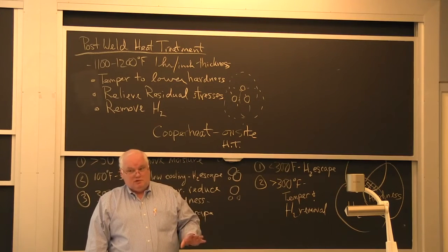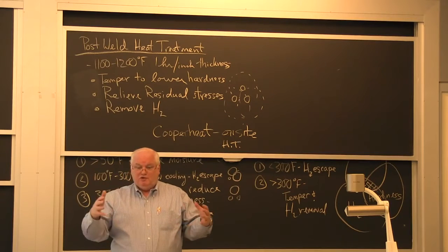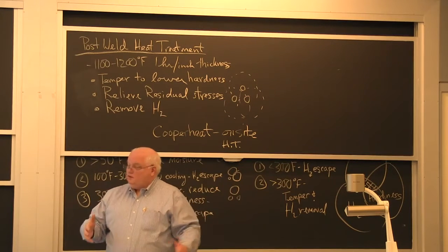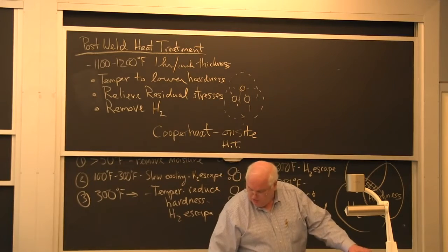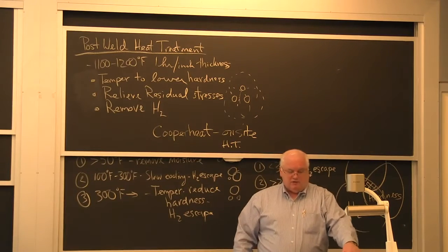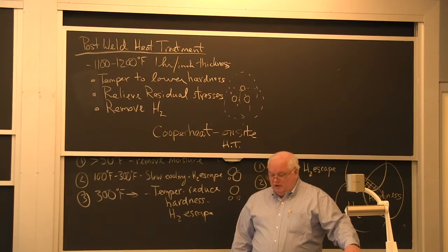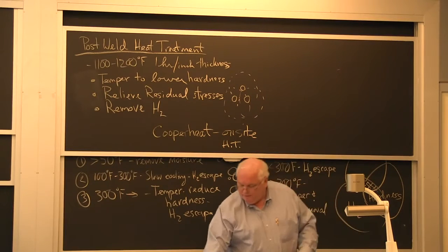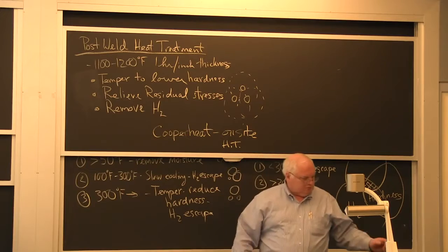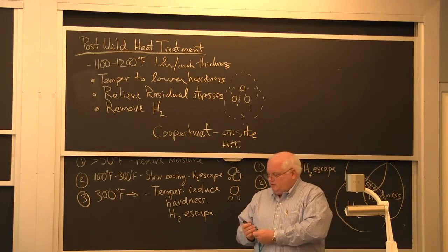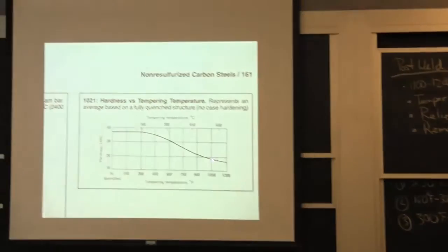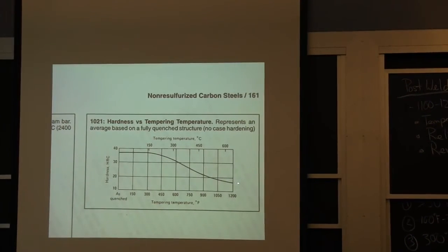There are all kinds of rules on local heat treatment, because if you do local heat treatment somewhere, you're going to get into this intermediate range where you get temper brittleness, okay? You don't like to be in the 600 to 1,000 degree tempering range. Between here and here, you're going to be here. If you're doing local heat treatment, obviously something's cold back here, something is in the intermediate range, and you could damage your steel, depending on the type of steel, by doing local stress relief.